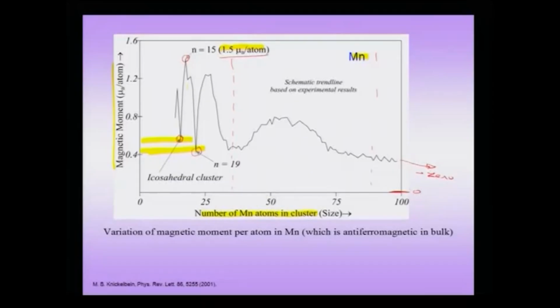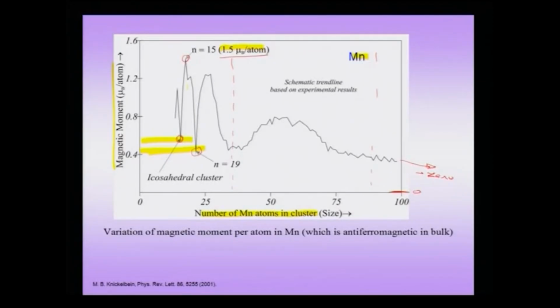And in the small cluster regime, like in the case of ferromagnetic clusters, there are large oscillations, and these oscillations finally die down, and you obtain what is called the large cluster regime, and finally the nanocrystal regime. Additionally, we noted that to understand the variation in magnetization in these small clusters, we can invoke the principles we used in the case of the iron clusters. In other words, the icosahedral or close packing in these crystals is expected to give us these large variations in the magnetization. So, this is a very interesting possibility that actually you are seeing ferromagnetism in small clusters of an antiferromagnetic material.